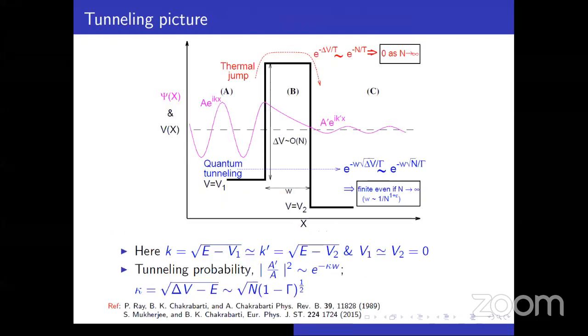So let me come to the next slide, the tunneling picture. Suppose you have a simplistic situation with one barrier of height of the order of N, delta V, as I have written in the middle. On the left-hand side there is a potential V1, which is much smaller than the barrier height, and outside you have V2, which is slightly less than V1. In a thermodynamic system, you can give sufficient time and temperature, and thermal noise will take the system out. What would be the escape time? The barrier escape time: you can see the thermal jump probability written there. It is exponentially decreasing with the barrier divided by the noise. The kinetic energy has to occasionally reach that value, and that will be the probability to get out.